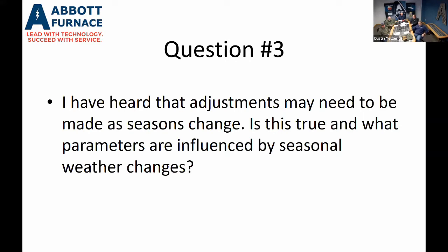Sometimes we need to increase the flow in the rear of the furnace a little bit in the curtain boxes to give us a little more positive pressure. Sometimes we need to come in and rebalance and turn the rotary injectors a little bit. And then as the weather warms up in the spring, it may require another change. Now, when we start opening windows, garage doors, and letting all that air in the building, then we might have issues with it actually coming in through the furnace doors itself, and adjustments to the rear curtains, replacement of the rear curtains if they're worn. And again, sometimes a change in the atmosphere flows and volumes are required to fight that issue. Yep. Very good. It's an appropriate question when it was 9 degrees out this morning.